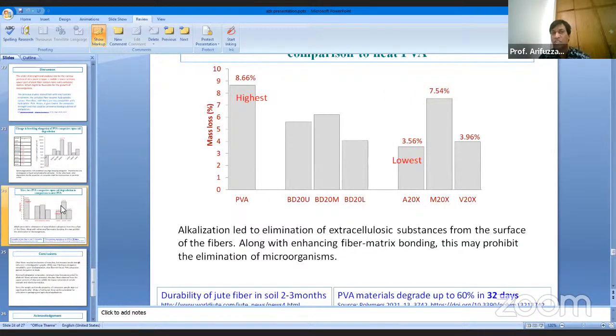The figure shows the weight loss after degradation. We have seen that the highest loss of weight is found for the polyvinyl alcohol sample, and lower weight loss is found for the composite sample. The lowest loss of weight is found for the alkali treated sample. Alkalization led to eliminating the extracellulosic substance from the surface of the fiber, along with enhancing fiber matrix bonding. This may prohibit the elimination of microorganisms.